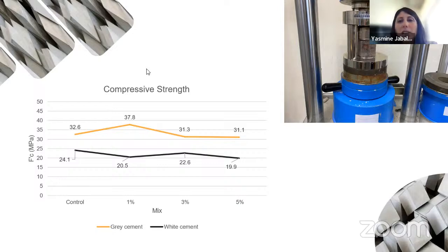Concerning the terminology, we're just using this to label some of the mortars and to create a difference between the labeling. Concerning the percentages of TiO2, the study started about 3 years ago. We started working first on TiO2 paste, with percentages of 1, 5, and 10. Then we noticed that the best performance is between 1 and 5, so we tried reducing those percentages to 1, 3, and 5, and integrating the TiO2 in the cementitious mix itself.